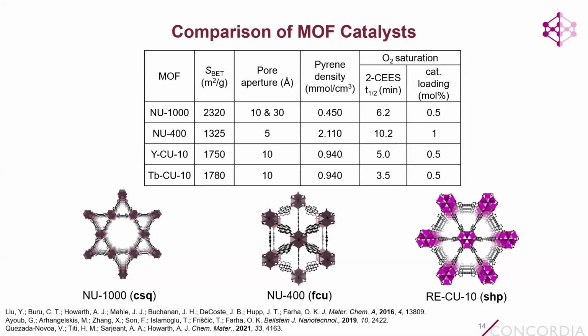So we can look at the pore aperture size as well as the density of pyrene chromophores, okay? So the pore aperture size is important for the diffusion of reactants and products, which is going to be important for a catalyst. But the density of pyrene chromophores should also be important for the generation of singlet oxygen, right? And so if we look at NU1000, it has these really large 30 angstrom pore apertures, so great for diffusion, which is why it's such an excellent catalyst for lots of other applications. But it has a very low density of pyrene chromophores. So it ultimately gives rise to this kind of moderate half-life that we see of 6.2 minutes.